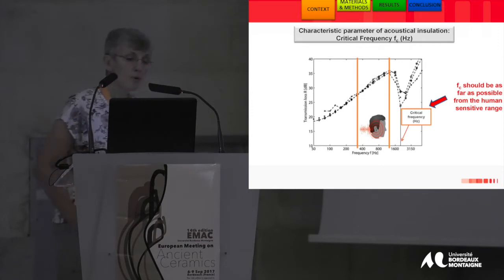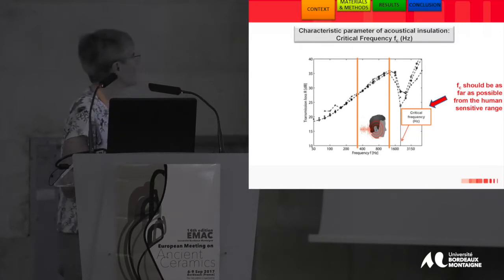Second important parameter is what we call the critical frequency. On this graph, you have the transmission loss as a function of frequency, so it increases with frequency. But there is a specific frequency which is quite detrimental because there is a sudden drop of the sound transmission loss due to resonance phenomena. What we are looking for is to have this critical frequency as far as possible from the human sensitive range, which is between 300 and 1500 hertz.